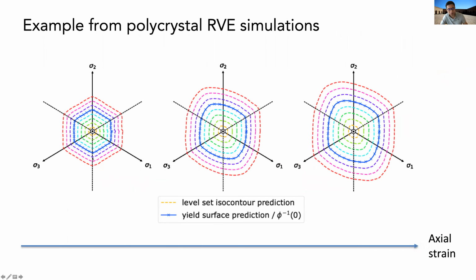This is one example of the level set that is trained from RVE of polycrystal. As you see, it starts out simply looking like a Tresca model. As we load it more, it generates something new. I found it quite interesting in the sense that it actually changed the shape. The hardening is not isotropic because it's not just enlarging the Tresca model, but actually changing the shape as we are yielding it.